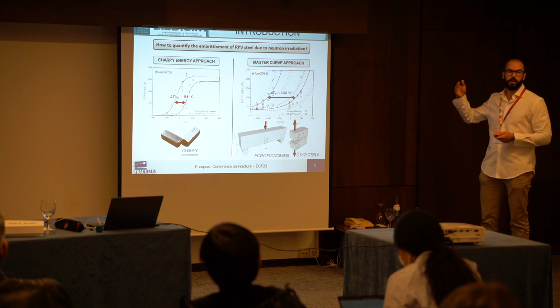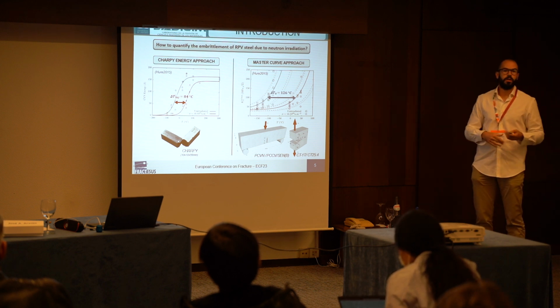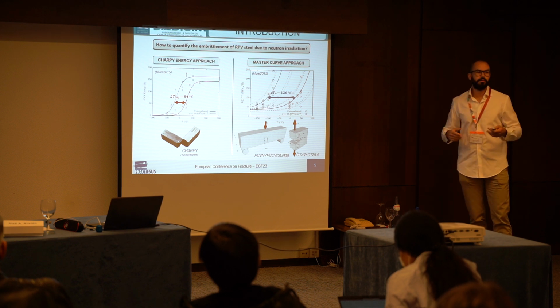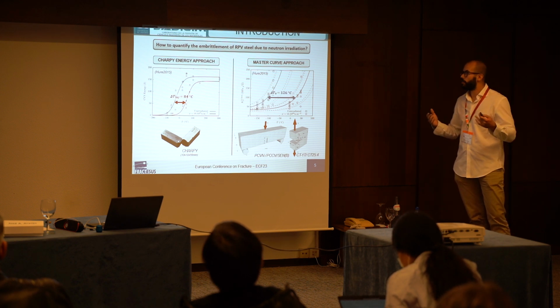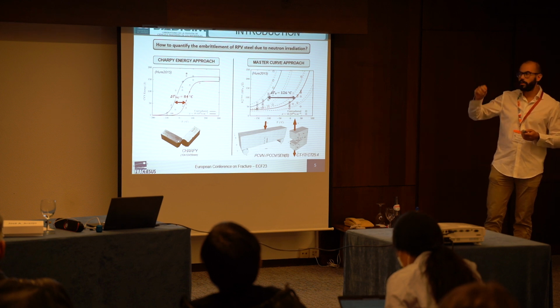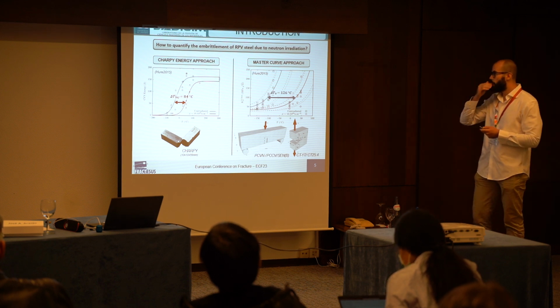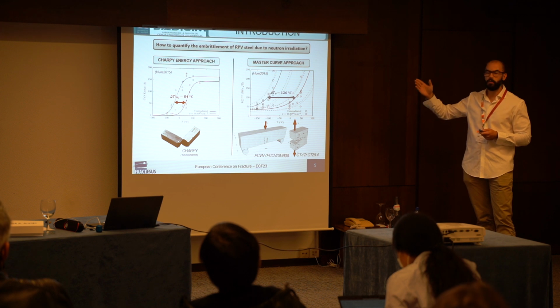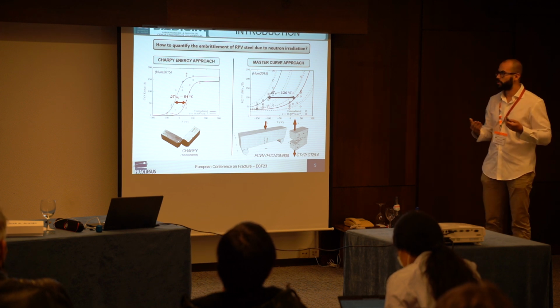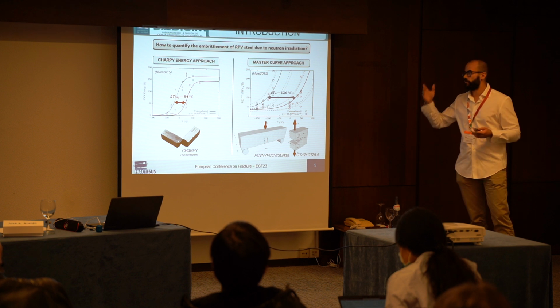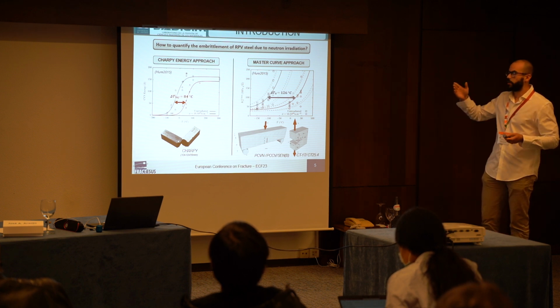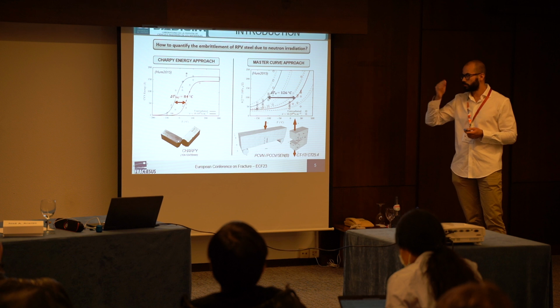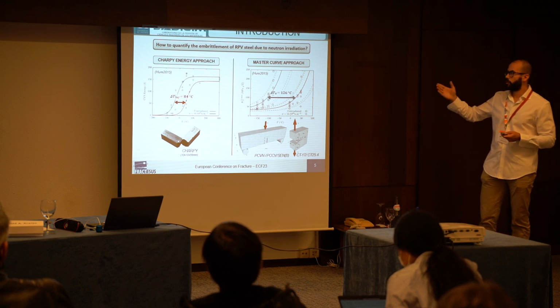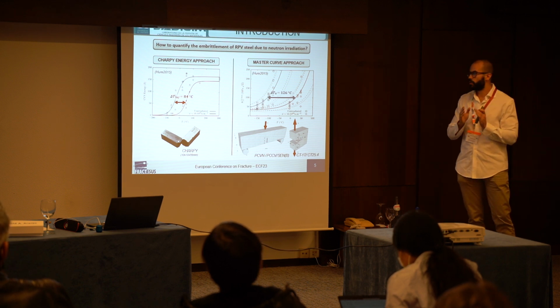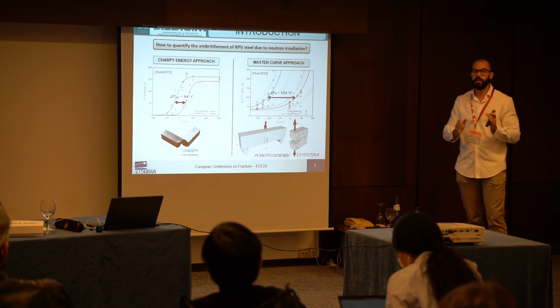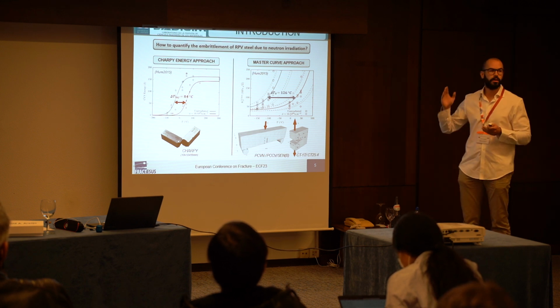This well-known approach allows us to determine the fracture toughness within the ductile to brittle transition zone. So, in this sense, the master curve methodology is more interesting for us because by just knowing a single parameter, the reference temperature, we can obtain the fracture toughness for any temperature. In both methodologies, the irradiation can be quantified as the shift between the unirradiated curve and the irradiated one.